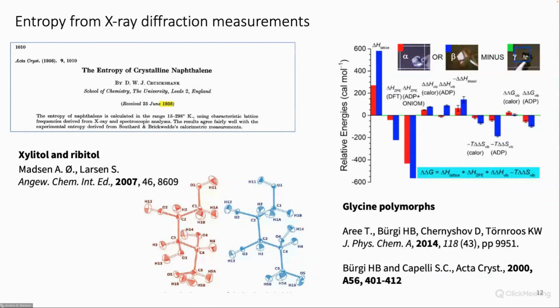We have done something a little similar in the case of these two compounds, ribitol and xylitol, where we showed that one of the forms actually is stabilized by entropy. And that was also using this TLS approach, whereas Hans-Beat Bürgi and co-workers have been working on a more thorough, very elegant approach, where you use many different temperatures and refine one common model to many different